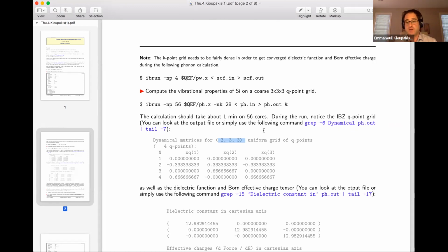But in principle, you could calculate the temperature-dependent band structure and enter that as your eigenvalue, or you could shift the spectra to account for the shifting band gap. That's what we do in the publication for silicon. We had to manually shift the spectra to capture this temperature dependence of the band gap, which is the dominant term that matters here.